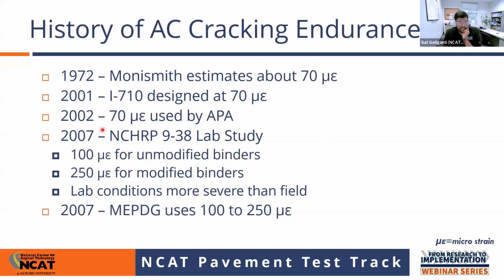And in 2007, as part of the big NCHRP project that Dr. Ray Brown at NCAT led, which was a laboratory study where we were testing a bunch of beam fatigue tests, what Dr. Ray Brown and his team were able to come up with was for unmodified binders, that strain criterion is not 70, it's basically 100 microstrain. And once you start looking at mixes with modified binders, that endurance limit criterion is even higher, which is 250 microstrain.